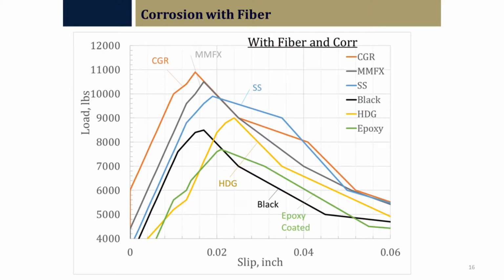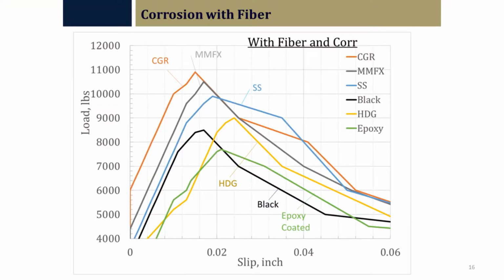So comparing that to the next, adding corrosion into it with fiber, you can still see a similar result where galvanized and stainless steel, MMFX, and continuous are above uncoated and epoxy, but slightly lower and slightly more towards the right. So you go back and compare that to this. That's a little bit different.